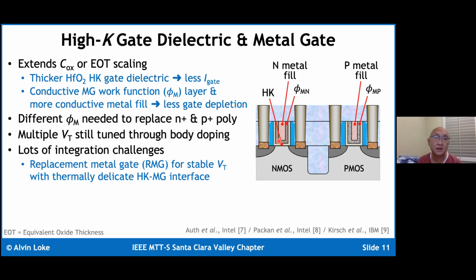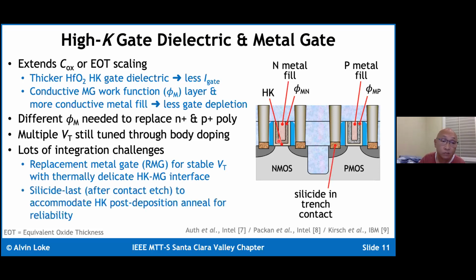For one, the industry had to adopt what's referred to as a replacement metal gate technology, such that you have a stable VT. The reason is the HighK metal gate interface is thermally unstable. If you were to expose the HighK metal gate interface to the high temperature source drain anneals that you need to activate the dopants after implant, that can cause the VTs to shift dramatically in your transistors. In fact, I've seen, for instance, PMOS VTs as high as 0.7, 0.8 volts, which would render the technology useless.